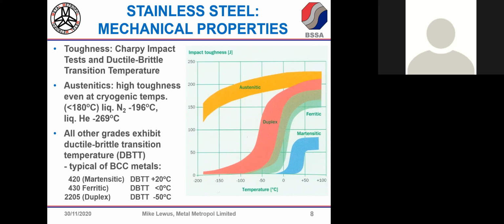But the point on this slide, you'll see that all those families, with the exception of the austenitic, the orange band, they all have a big interruption in this plot that shows impact toughness versus temperature. So if we're talking about any applications where components are exposed to very low temperatures, there's only one family you're going to select the material grade from, and it's going to be an austenitic. Of course, duplex grades have transitions going from behavior that's essentially ductile to brittle at fairly low temperatures, you know, minus 50 and lower. So that's not really going to trouble us. It's not going to prevent us selecting those in certain marine applications.